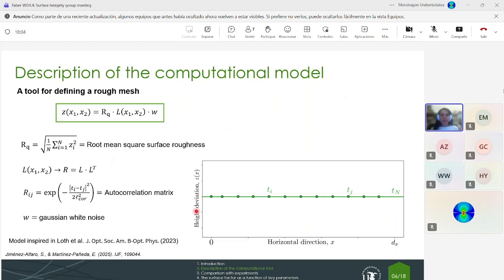Basically, the main idea behind this is that we deviate different points in a nominal surface, meaning the same surface without the surface roughness, following a mathematical function that is here. You can see that it is the product of the root mean square surface roughness, the matrix L, that is the Cholesky decomposition of the autocorrelation matrix, and then the Gaussian white noise. This Gaussian white noise is the one responsible for the stochastic phenomenon.